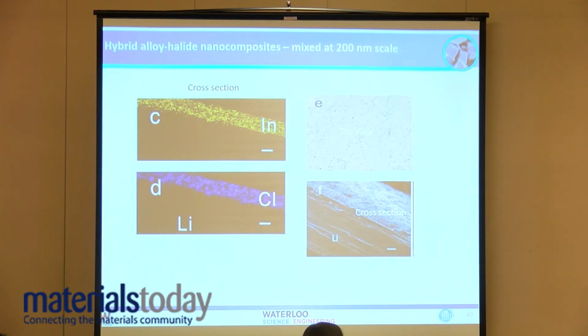So this just shows the cross-section of the alloy. This happens to be for indium, where you can see the population of indium in this film. It's about 5 microns, and it's not quite nano, but these components are mixed on the nano level, and here you can see the chlorine in blue if it's visible. This is showing the top of the cross-section of the film and then the top layer.